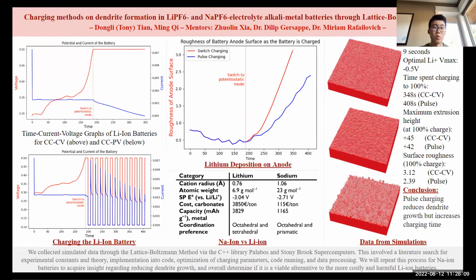Methods of reducing dendrite growth for lithium are already proposed, but our goal is to determine if they are viable for sodium. We first compared 2 forms of charging methods, CCCV and pulse, on their charging effectiveness and their limitation of dendrite growth in lithium batteries. CCCV charging is shown in the top left graph, charging at a constant current and then switching to a constant voltage, while pulse charging is shown in the bottom left graph, giving the battery regular breaks to absorb the lithium ions.